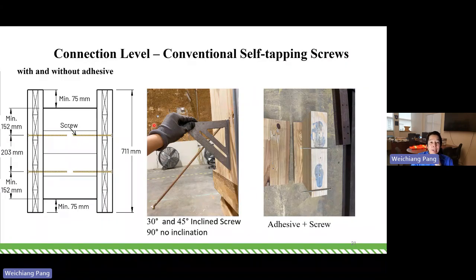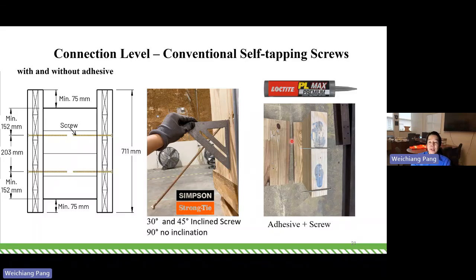So this is what the connections looked like. Self-tapping screws: we tested different kinds of screws, with and without adhesive, at different angles, 30 degrees, 45, and even 90 degrees, meaning there's no inclination, just like what the drawing here showed, a screw at a 90-degree angle. Some of those we put adhesive in between, some without adhesive. This is Simpson, and this is the Loctite glue here.